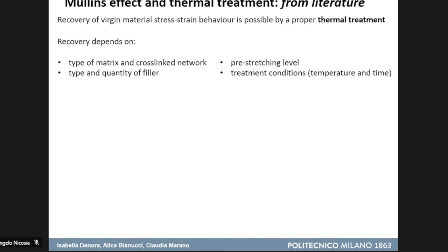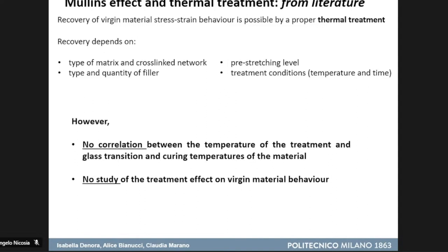This recovery is possible just in some conditions, and it depends on the type of matrix and filler, on pre-stretching level, and also on the conditions of the thermal treatment that we apply. However, no correlation is present between the temperature of the treatment and the glass transition and curing temperatures of the materials. And moreover, there's no study in literature about the effect on virgin material mechanical behavior.